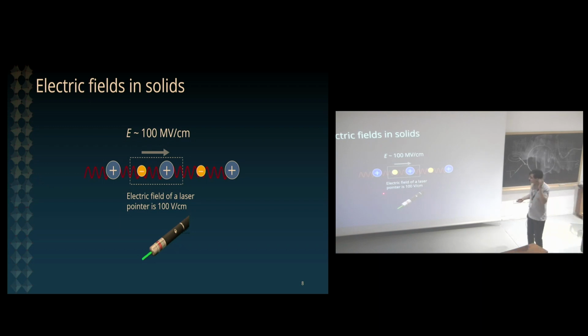Right. So now, before we continue, let's ask ourselves a fundamental question. What type of laser pulse do I need to use in order to induce some significant structural dynamics? Okay. So the laser pointer that I'm using here carries an electric field of the order of 100 volt per centimeter. And we're all familiar with the interatomic electric fields in our ionic type of materials. These are hundreds of megavolt per centimeter typically. So this laser pointer, even if it was tuned in resonance with a phonon, is not going to induce very significant changes in atomic positions.